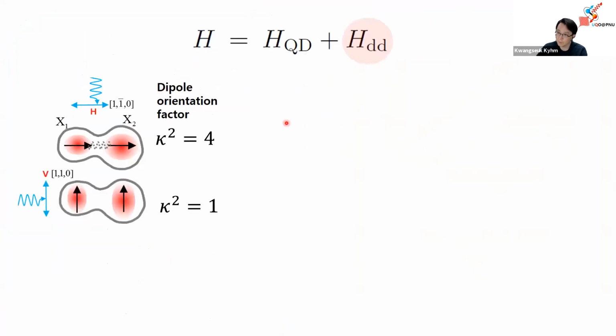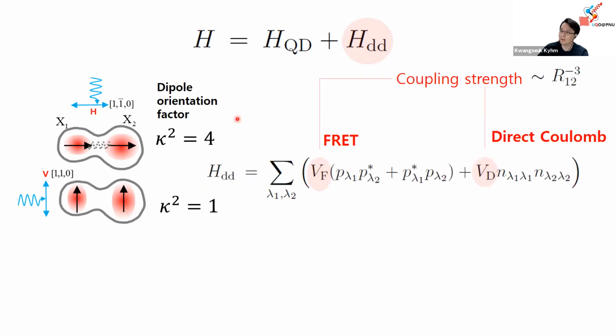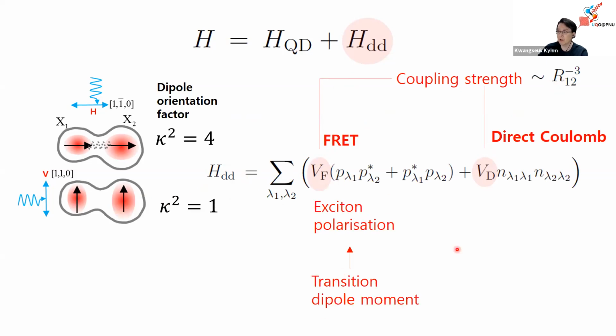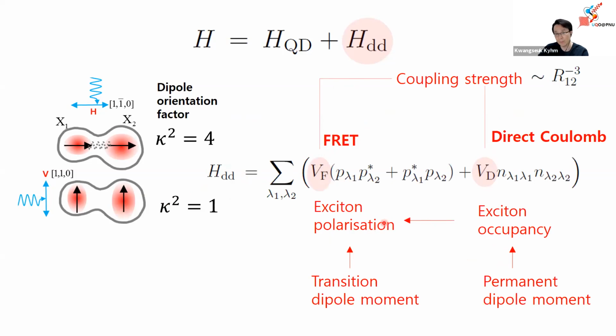To analyze it, we made a model based on dipole-dipole interaction. Again here, orientation and alignment are very important. In dipole-dipole interaction, people define a dipole orientation factor. For example, here this is 4, and this is 1. The dipole interaction more specifically consists of two different terms: one is Förster resonant energy transfer, and the other is the direct Coulomb interaction. The magnitude has the same distance dependence, the distance between two dipoles, but the mechanism is a bit different. One is about the transition dipole moment, and the other is about the permanent dipole moment, in other words occupancy. Occupancy also affects the polarization, so it's kind of a nonlinear effect. As occupancy is increased, the wave function is modified, and the oscillator strength is modified.